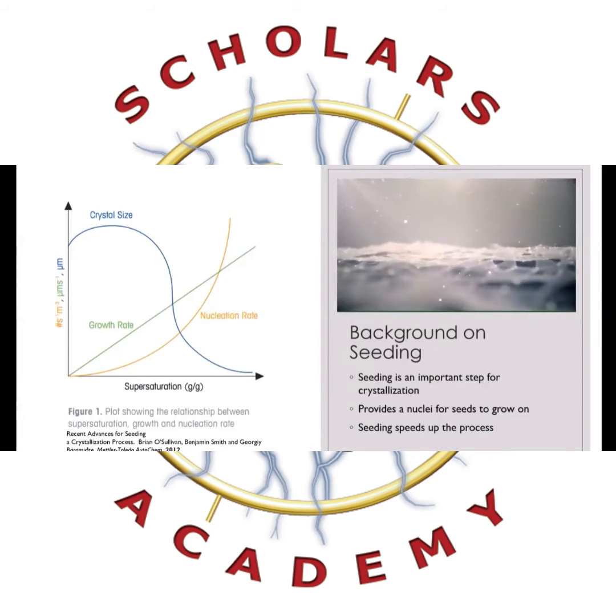Now, in reality, the nucleation process, which is a function of supersaturation as is particle growth, can never be fully quenched. For example, see Figure 1. Therefore, there will always be some level of nucleation even in the presence of seed particles. The level of nucleation is a function of the rate of supersaturation generation during the process and becomes a critical parameter that must be optimized with the seeding step itself. So here on the left-hand side, I have a plot showing the relationship between supersaturation, growth, and nucleation rate.